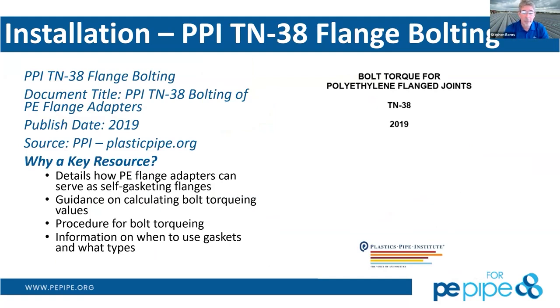So if you can't do a butt fusion or electrofusion, you may need to do a flange adapter. Flange adapters are very common to flange up to an appurtenance. Maybe it's a tank, maybe it's a valve, maybe it's a flow meter, whatever it might be. There are flange adapters available, what they call stub ends, that you fuse onto the polyethylene pipe, typically with a butt fusion. And that then allows you to flange up to another appurtenance. So PPI's TN38 is how you go about doing that, and more importantly, how you go about torquing those bolts to make sure you get a nice, even compression of that flange adapter.